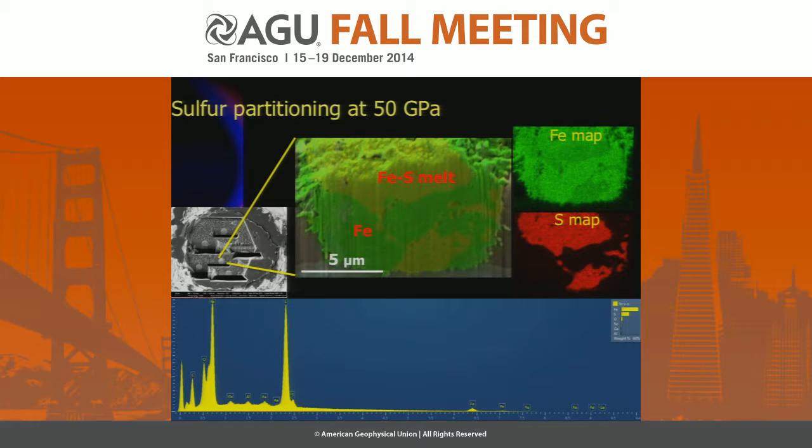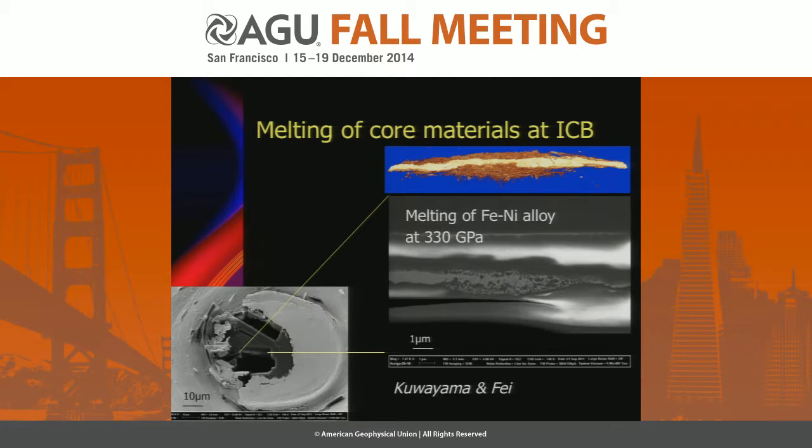Again, with this sample design technique, we can confine the melting. We can really look at the coexisting solid and liquid phases and be able to do the phase diagram. And ultimately, we want to take this type of protocol and measurement beyond to very high pressure. And obviously, those are much more costly and challenging.